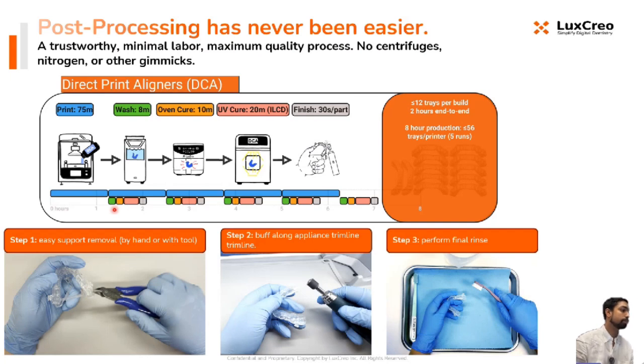The parts are then automatically drained and they're left in the basket, devoid of IPA, and the parts are perfectly clean. You then take the parts and put them in the oven cure, and you just press the program setting P1, and in 10 minutes the heat treatment will be completed.